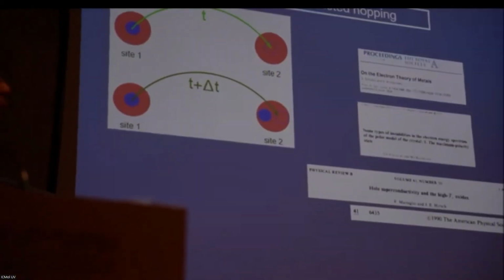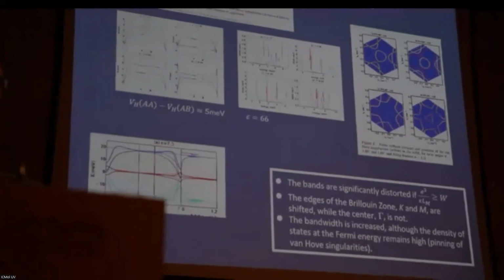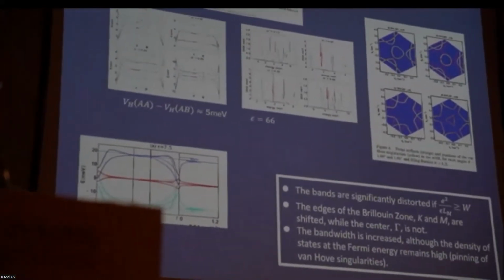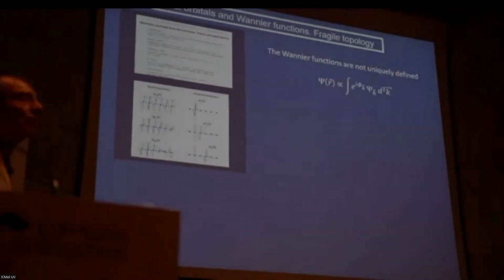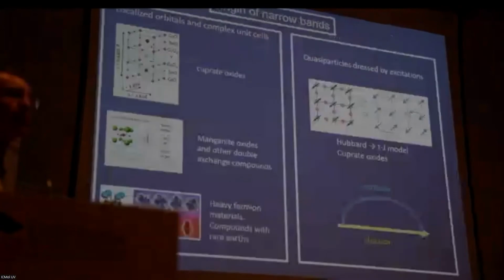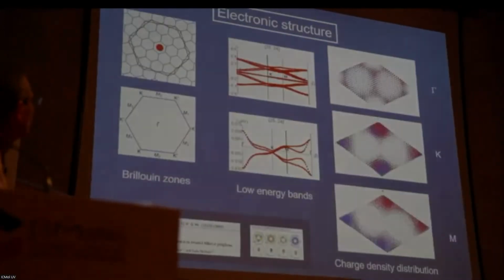Actually, that's interesting because it turns out the trilayer is a very special situation because you have one layer, then you rotate the other a little bit, and then the third layer has to coincide with the first layer. But it turns out, according to, for instance, Philip Kim at Harvard and Pablo Jarillo-Herrero at MIT, that it's very stable and it's very nice. Nobody knows for sure how many of the twisted bilayers work, depending on which experimentalist you ask. He or she will tell you maybe 1/5, maybe 20%, maybe 25%, maybe half. In the case of trilayers, it seems that all of them work. All of them are superconducting. Let me see, because I mentioned that at the beginning.